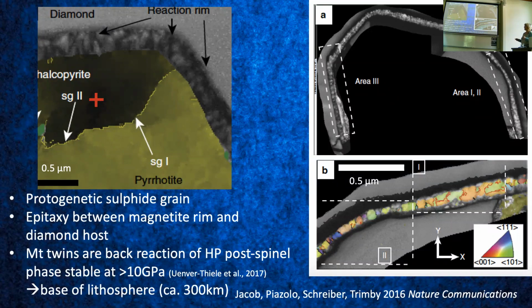I said again, the sulfide was already there before the diamond formed. We found that there's epitaxy, so the crystallographic orientations were aligned between the sulfide and the magnetite, and between the magnetite and the diamond, which is an absolutely clear sign that one grew on the other. So along the rim of the sulfide grew the magnetite, and the diamond nucleated and grew on the magnetite. This turned out to be the first direct observation of how diamond actually nucleates and starts forming.